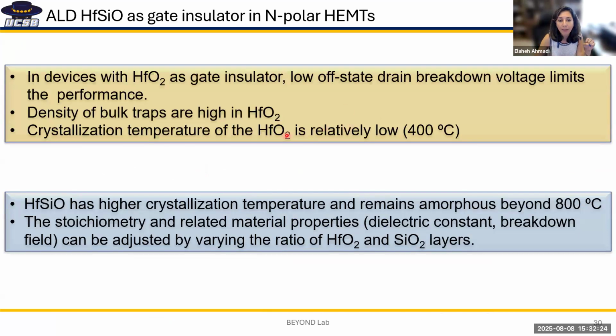But then we had seen separately in other works that we had done with aluminum silicon oxide. One thing we had seen is that hafnium oxide starts crystallizing at a relatively low temperature, 400 C, which is the post deposition annealing temperature that we were using, and these grains could be a current leakage path. And we had seen separately, and this was actually in Mishra's group when they were doing aluminum silicon oxide, that by adding silicon oxide, they increased the crystallization temperature of aluminum oxide when they were doing it by MOCVD. So that kind of motivated us to look at hafnium silicon oxide.